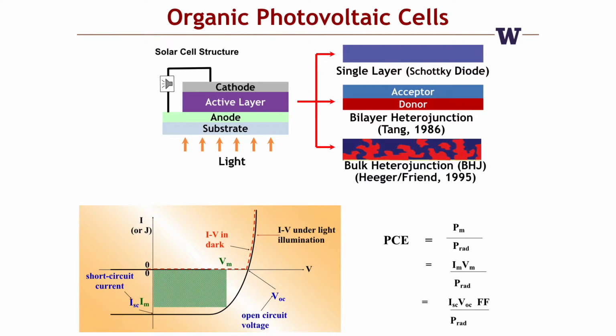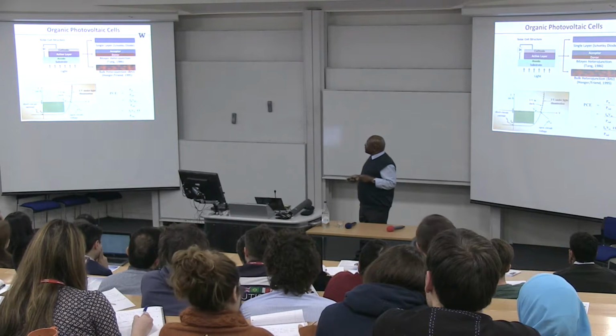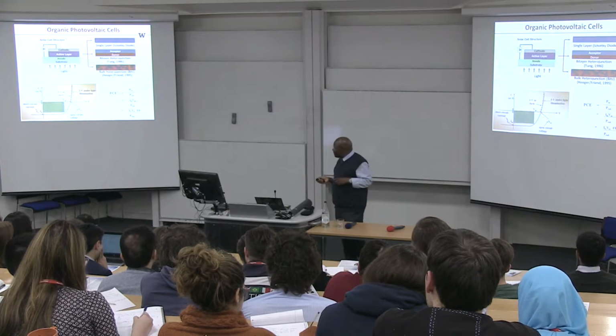as we shall see. So typically, this is a typical solar cell. So you have two electrodes, the active layer, and over time there has been evolution of what that active layer should be, the organic semiconductor active layer. What has been found in order to indeed create these interfaces between two materials, the donor and the acceptor, is to have a blend, otherwise known as a bulk heterojunction, so that if done properly, then you have sufficient interfaces to have efficient devices.